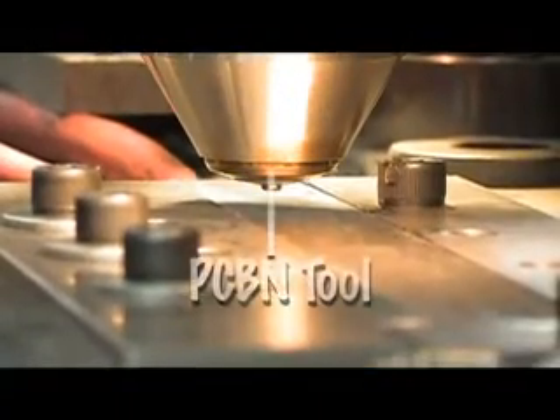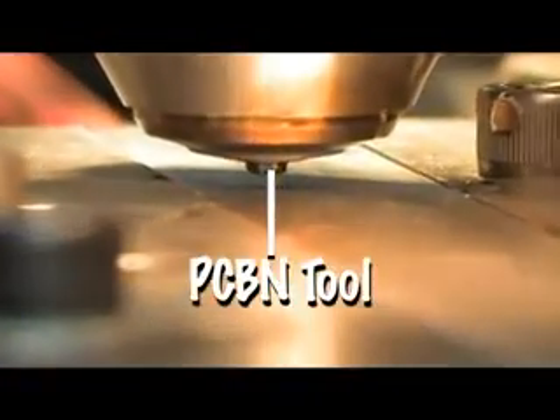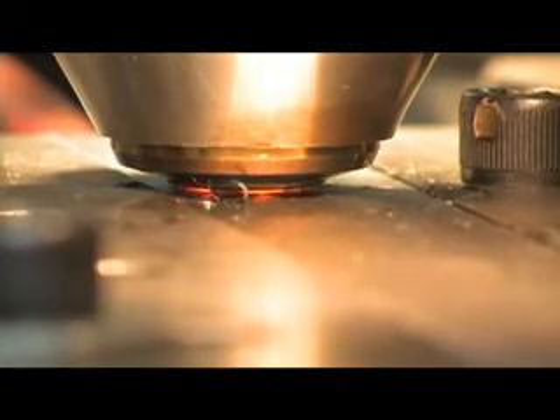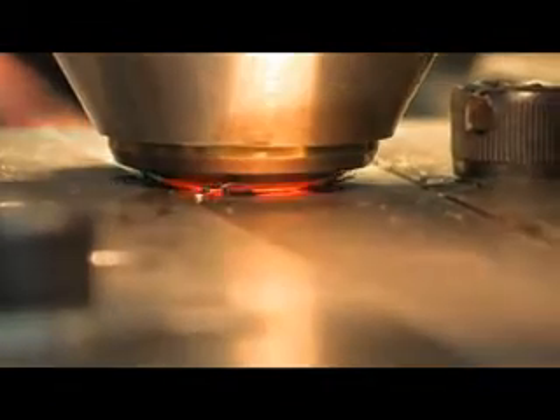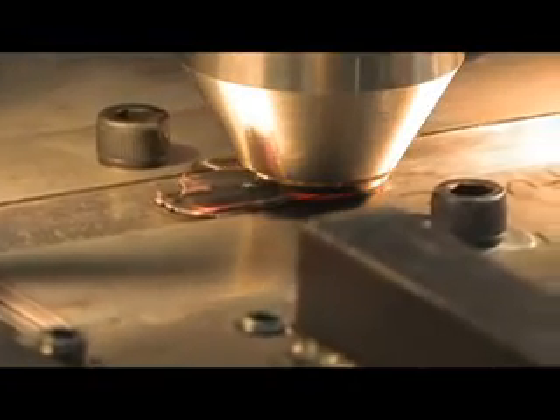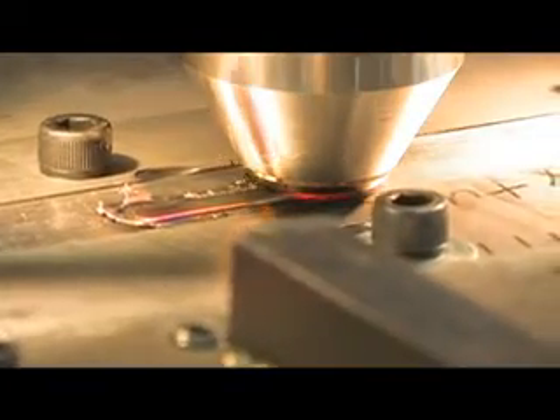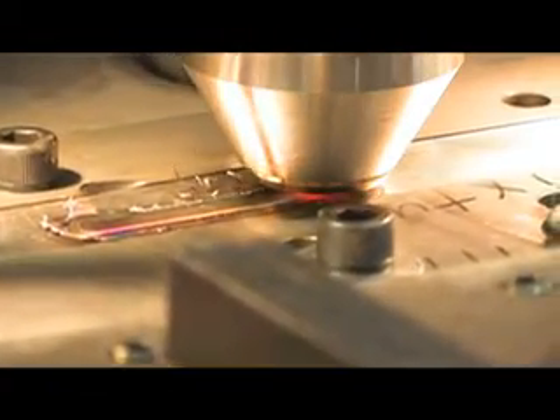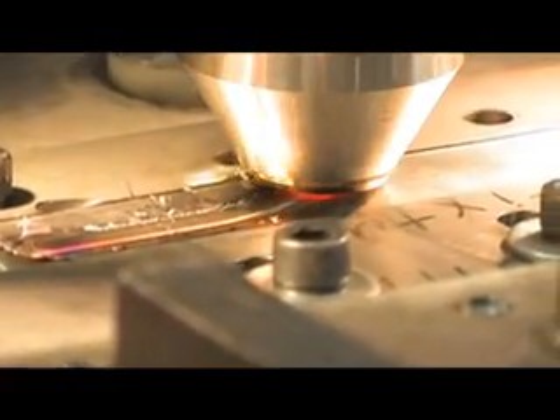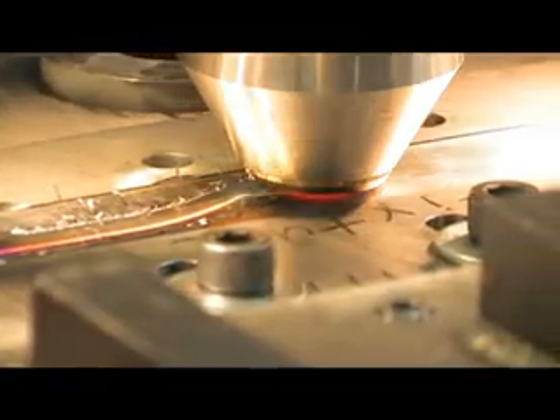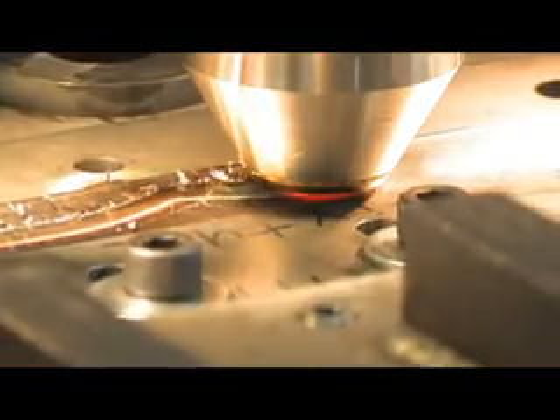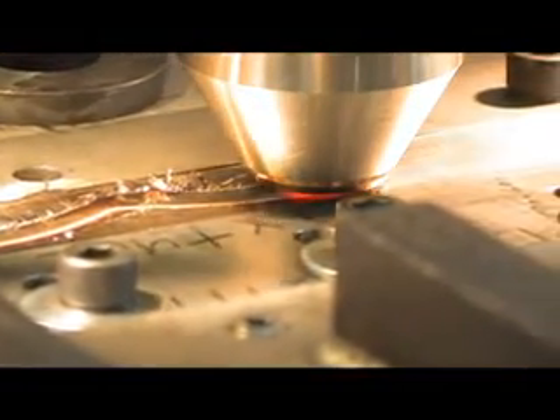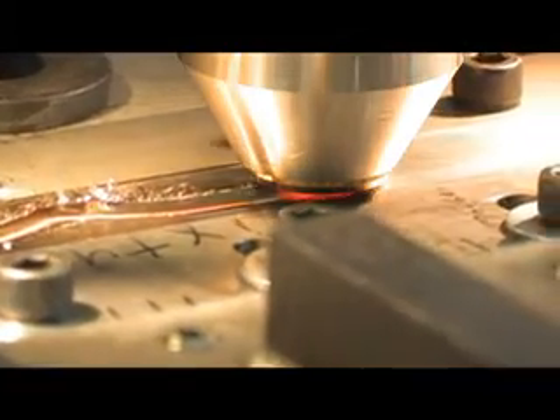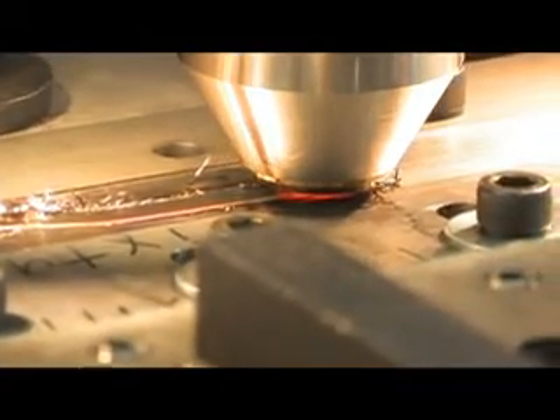The polycrystalline cubic boron nitride, or PCBN tool, rotates counterclockwise with multiple tons of friction forging downforce into the D2 steel. The friction forging area plasticizes the steel. The friction forged grains are nanosized at 0.5 microns, which are 10 times smaller than normal heat-treated D2 steel. The friction forged zone will have a Rockwell hardness between 65 and 68.